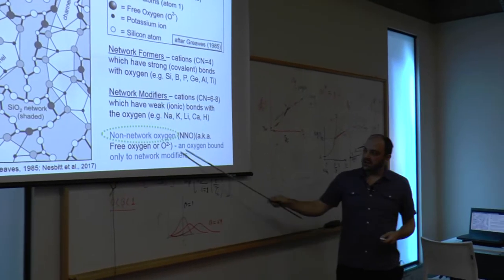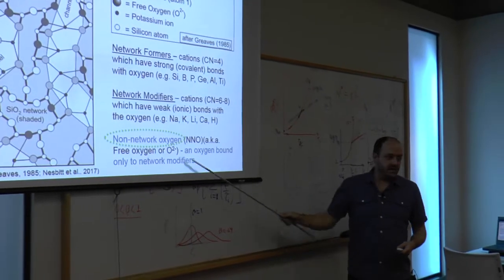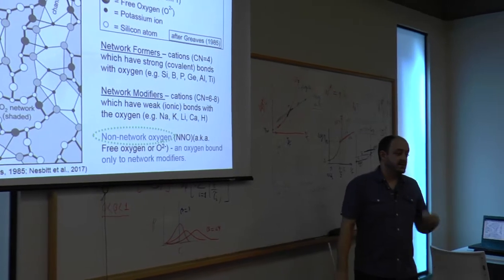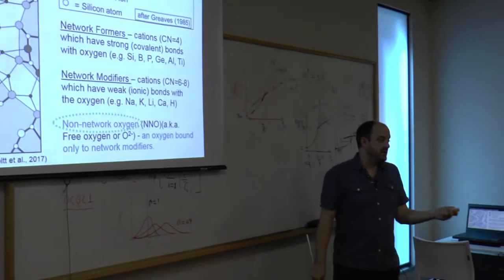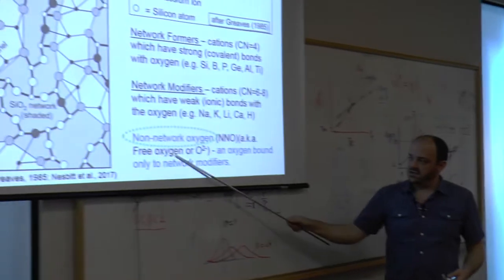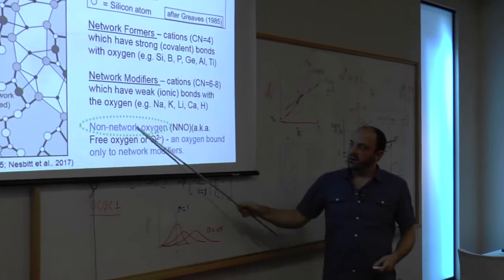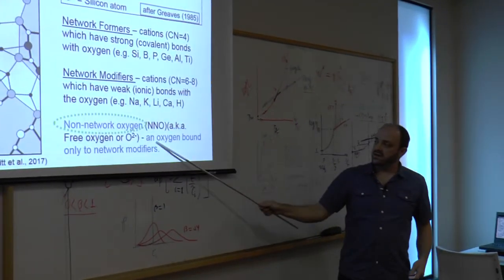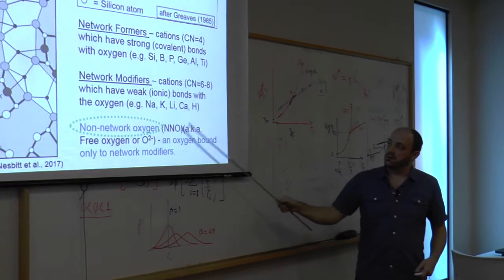Because the big confusion arises when you say O2 negative, this could be an oxygen atom that's not bound to the network. This is a free radical. So for me, free oxygen is a little bit confusing, and non-network oxygen makes more sense. And this is oxygen that's only bound to the network modifiers. Okay?